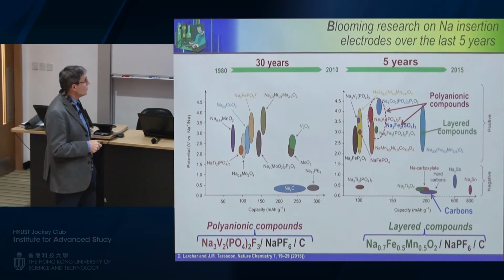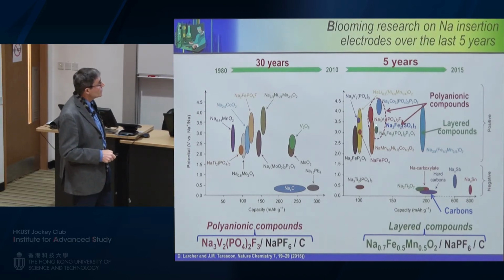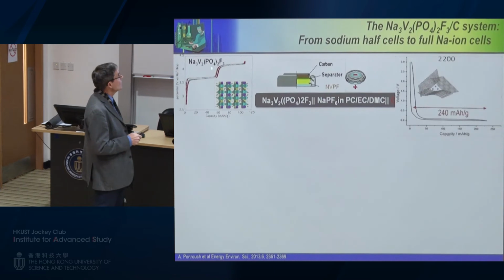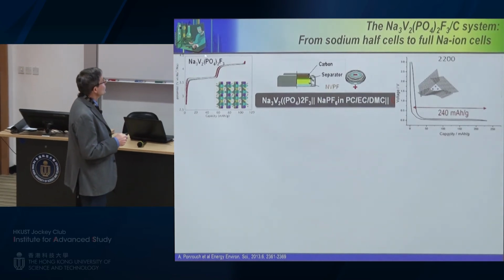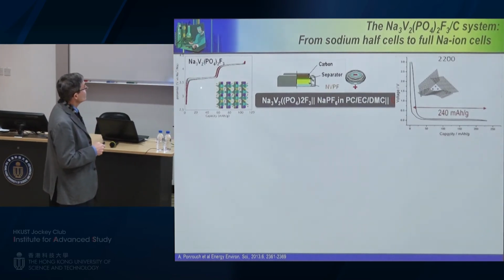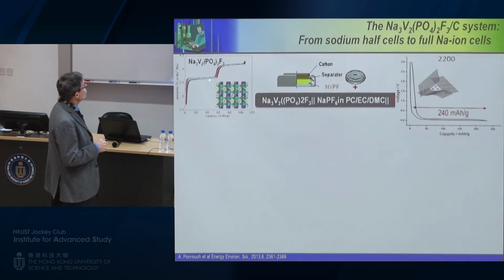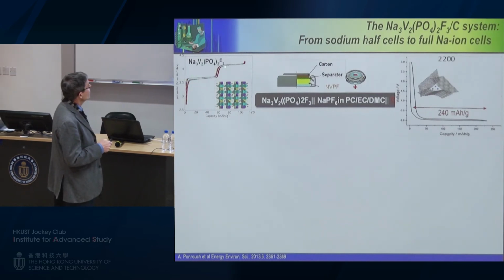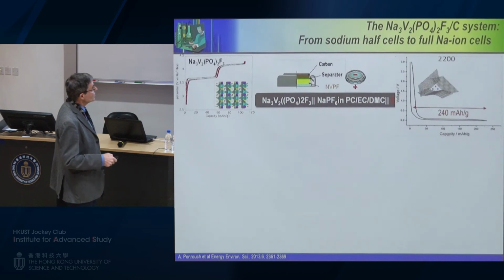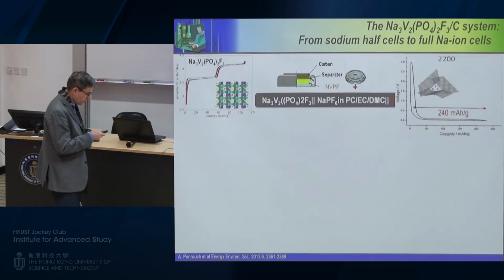So the system that we have been developing, as a matter of fact, is based on this compound, Na3V2(PO4)2F3, and carbon. So we focus on these systems, whose voltage-composition curve is clearly indicated here, with these two plateaus at about 3.6 and 4.2 volts, and we use in this case carbon as a negative electrode.